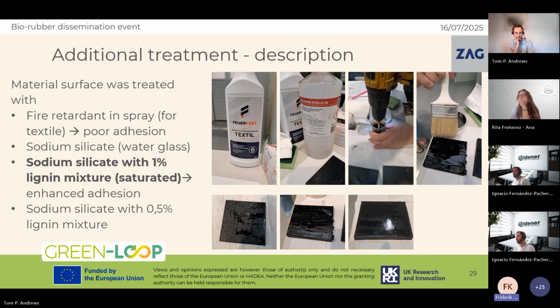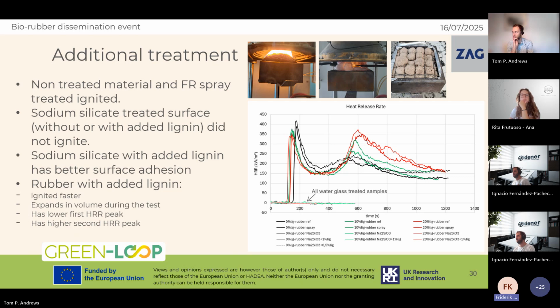And what we have for the result, next slide, please. So what we see here is, if we look at the three pictures, on the left side is with no treatment. You can see the intumescent, so the swelling effect of the rubber, but it is still burning. Whereas if it is covered with water glass, there is still swelling, but there is no burning. This is very nicely shown on the charts, where we can see on the lower part there was no ignition. So treatment with water glass or that sort of treatment of the surfaces may truly make the reaction to fire much lower.